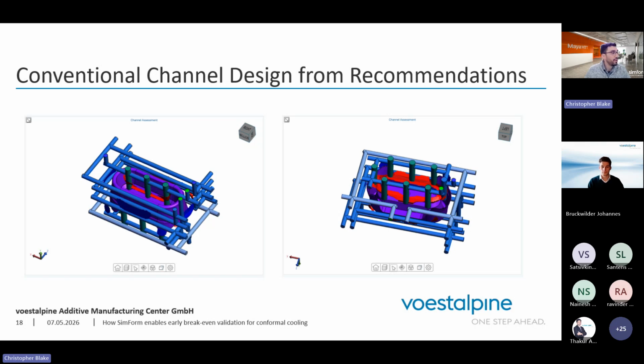In order to cool the concave areas of this medical tray, but still respect the spacing between the channels and how close we can get with our gun drilling technique, we have to introduce these baffles here to bring the cooling water closer to the concave region. So you see it here in the working surface area of the medical tray, and then also in the underside. But we can only go so deep because this is a very narrow area of the plastic part. So we know, unfortunately, we're going to be faced with some non-uniform cooling of the part. So the natural question is, can we do better than this?